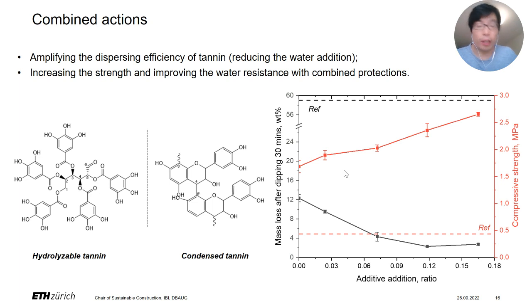Okay, so now we have the platform to work with, and then we can place things around. So yes, we have tannin as a dispersant to make our paste more liquid, and then we have the iron chloride to remove this dispersant effect slowly. So then we have some time to cast. And because all this reaction happened with the hydroxyl group of the tannin, we still have some other active site in the tannin, for instance, this side or this side.